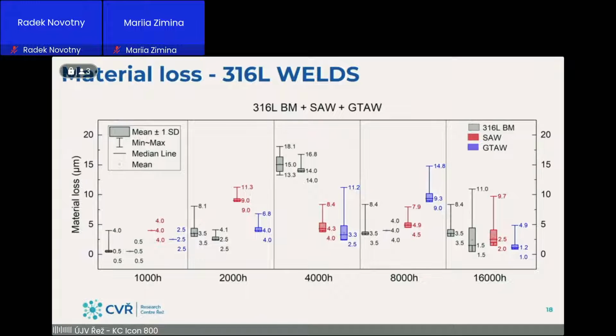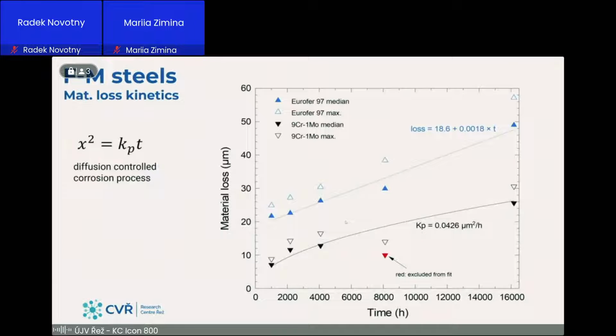This is a comparison of welds with base material. You can see there is no difference between the welds and 316L base material. So let's go back to the kinetics of stainless ferritic martensitic steel. If this corrosion process is diffusion controlled, that is what we want, we can fit the kinetics by a parabolic curve. That's possible for T91, but it's not possible to do that for Eurofer because it's gradually losing the oxide.